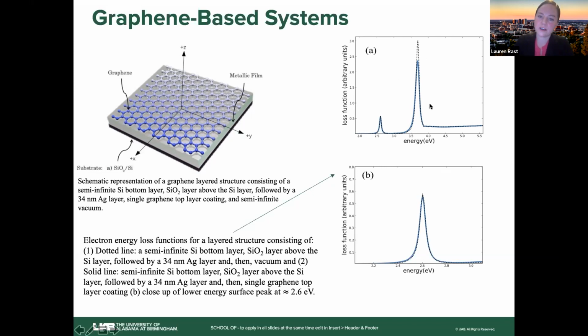In the results for the loss function over here, we have a dotted line for the semi-infinite silicon bottom layer, SiO2 layer, silver, and then vacuum. And then when we add the graphene layer on top, that's the solid line there. What we notice is a behavior that bears physical similarity to something called the Begrenzungs effect. Begrenzung is just a word that means boundary. This effect arises due to a reduction in the degree of freedom for the plasmonic excitation. So when we confine a plasmon in one dimension so that it's moving along the two-dimensional surface, what we notice is, you look at the B, there is the surface peak. That isn't changed, but we reduce coupling to the bulk peak on the right there.